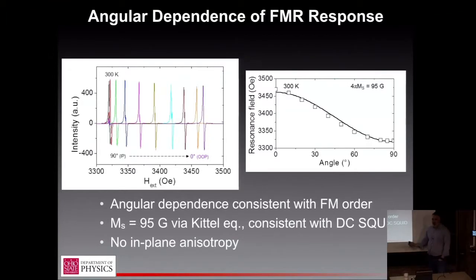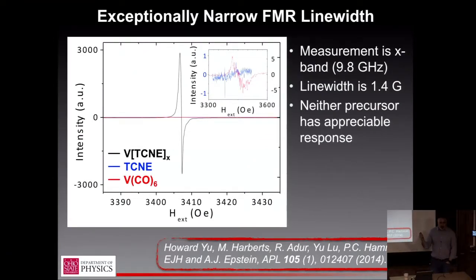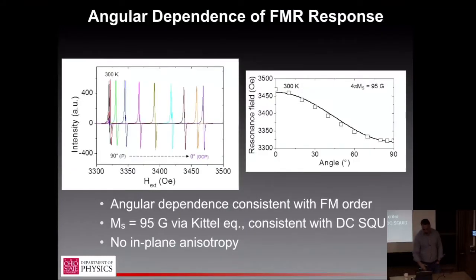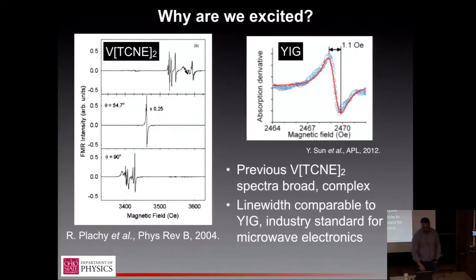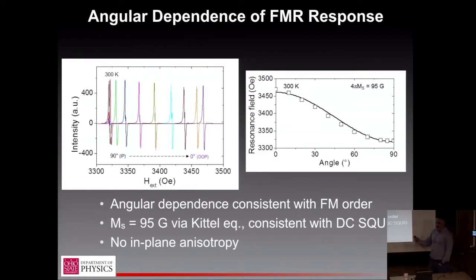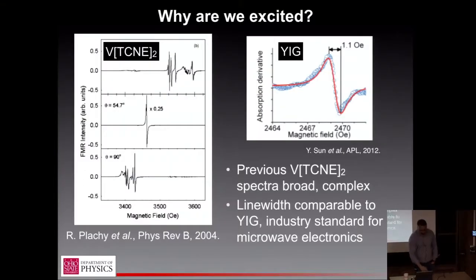So this got us really excited, and I have to admit, even when we had this data in hand, it took me a while to figure out that this would be interesting. This wasn't actually the direction we were going with this measurement, but to explain this, I'm showing two plots here. This is an older paper on VTCNE showing that even in films that show excellent DC magnetic properties, you have more of a forest of lines as you go from in plane to out of plane, and only at very special angles do you get that nice narrow FMR line. In contrast here, we see this 1 Gauss line width pretty much over the entire spectrum. So this is to say, Megan's hard work does mean something in the end.